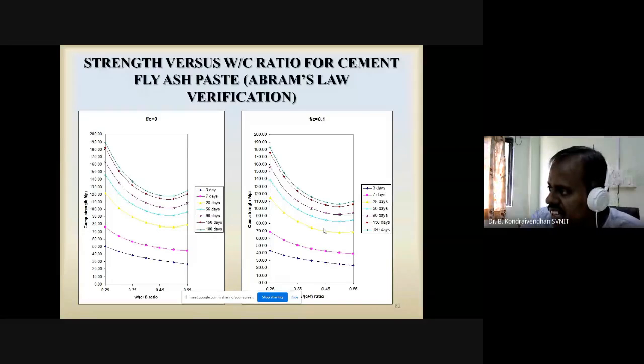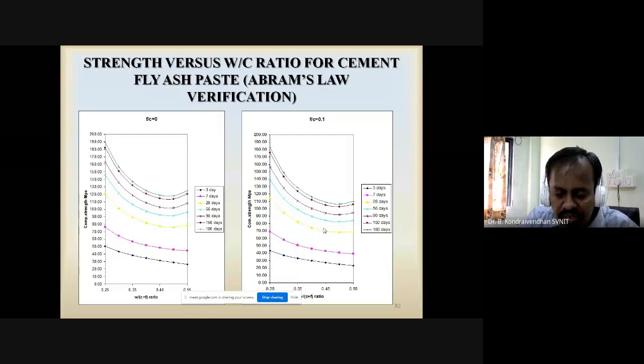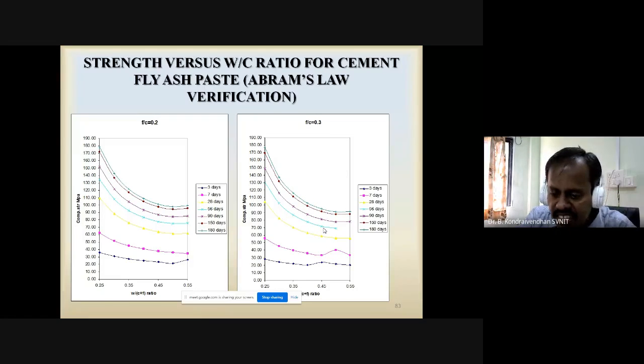Abram's law says that strength is inversely proportional to the water-cement ratio. So we are getting the same trend for different water-binder ratios, different curing ages, and different F by C ratios. We have done this for all these exercises and we got a similar trend. Now this is also correct. Like that we can ensure.